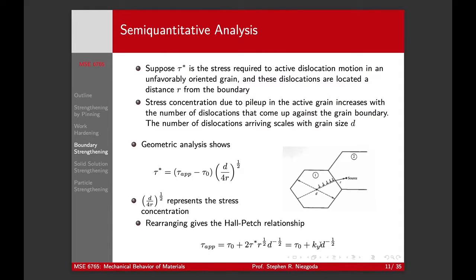Now remember, not all materials have the same Hall-Petch slope. Some materials are much less sensitive to the grain size than other materials. And also, we can see that this Hall-Petch slope depends on the pile-up behavior. So it's not too hard to imagine that it's also going to depend on the strain, because the more strain you have, the more dislocations, the bigger this pile-up is. And if I can get enough dislocations here fast enough, then I can break through. Okay.